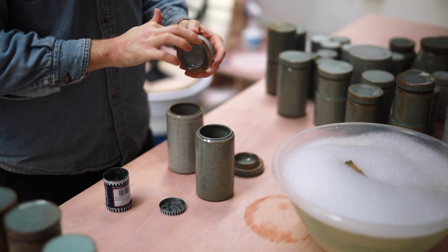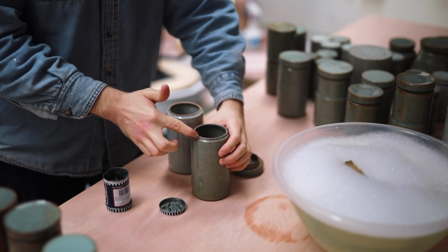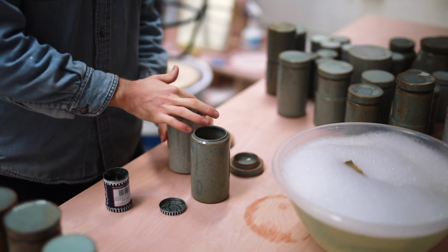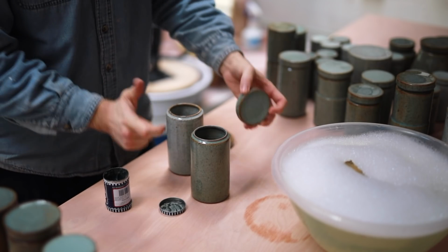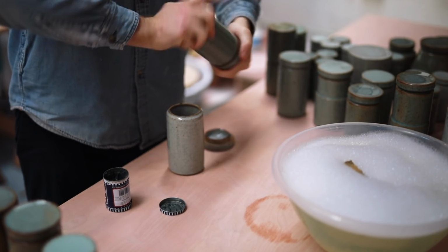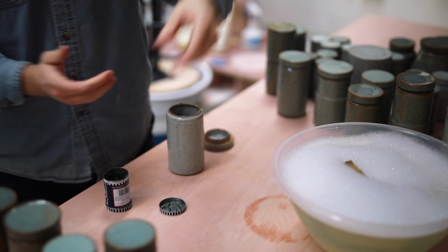Once it's all unpacked, I can finally begin the finishing procedures for the jars, which is a simple process really, and one I learnt from Lisa Hammond at Maze Hill Pottery during my 3-year apprenticeship with her. I rub over chemical valve grinding paste, which is essentially carborundum suspended in gel. It's placed in between the gallery, where the lid meets the body, and the two are ground in place together vigorously, and with enough elbow grease it can be glassy smooth by the time you're finished.